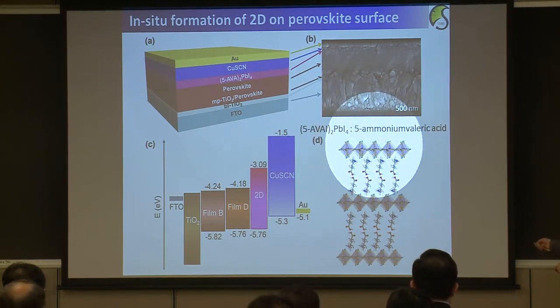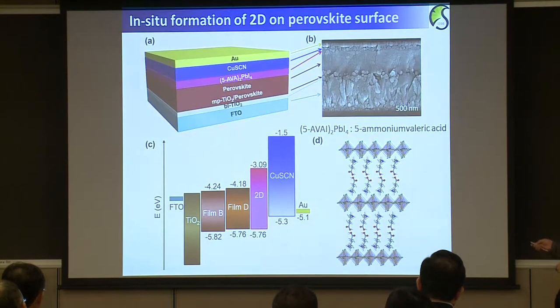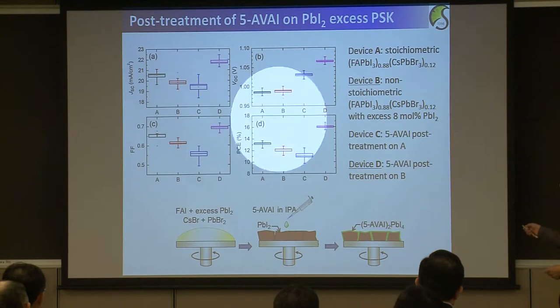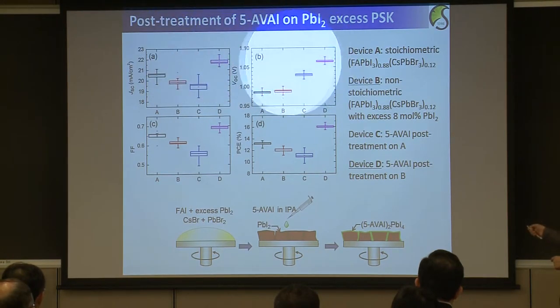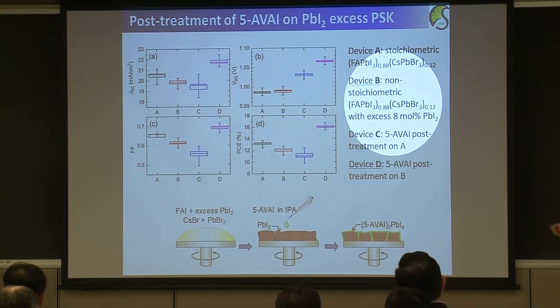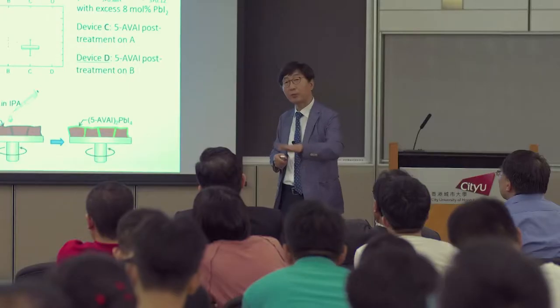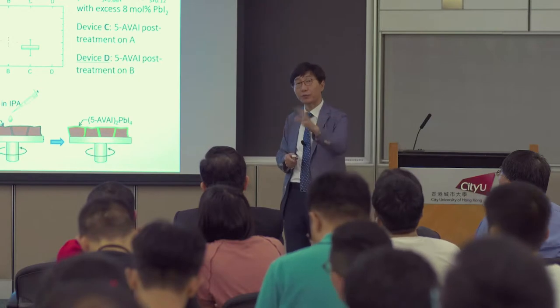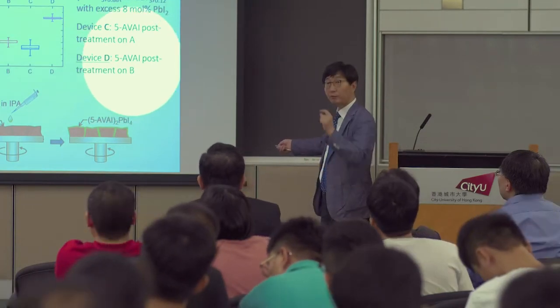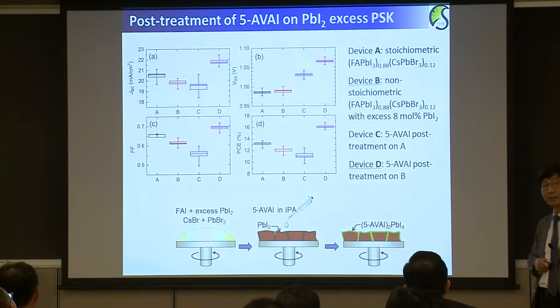Okay, this is 5-ammonium valeric acid, and then we form the two-dimensional structure on the surface of the perovskite using post-treatment. So first, we prepared the perovskite using a non-stoichiometric method, meaning that you slightly have the excess PbI2. And then after spin coating, you make the perovskite layer, and the excess PbI2 is probably sitting on the surface of the perovskite grain. And then we post-treat with this 5-AVAI to form the surface two-dimensional perovskite structure. The process is given here, okay?